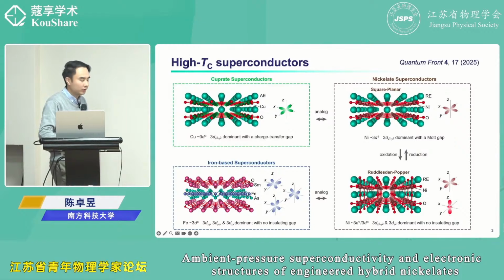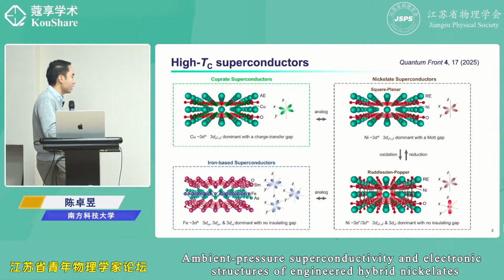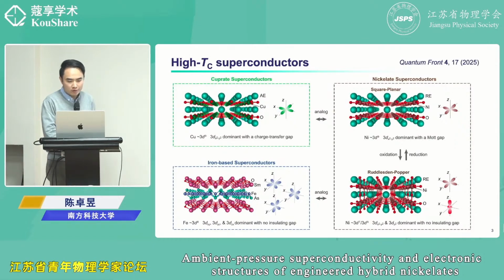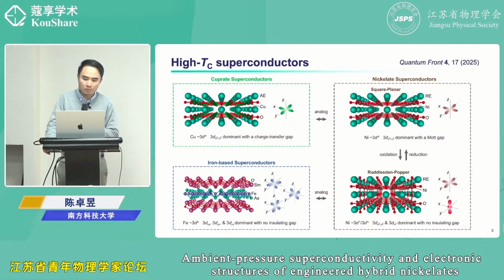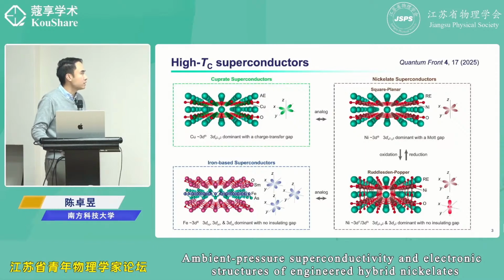For iron-based superconductors, it's quite different. It's a 3d6 electronic configuration, and it is a multi-band electronic structure near the Fermi level: the 3d xy, 3d yz, and 3d zx, these three orbitals. And quite recently, since 2019, nickelates have become superconducting. Nowadays, there are actually two quite distinct types of nickelate superconductors. One type we can call square planar. This type was first discovered to mimic cuprate superconductors. You can see the structure is very similar, almost the same. And the electronic structure is also 3d9, with the 3d dx²−y² orbital dominating near the Fermi level.